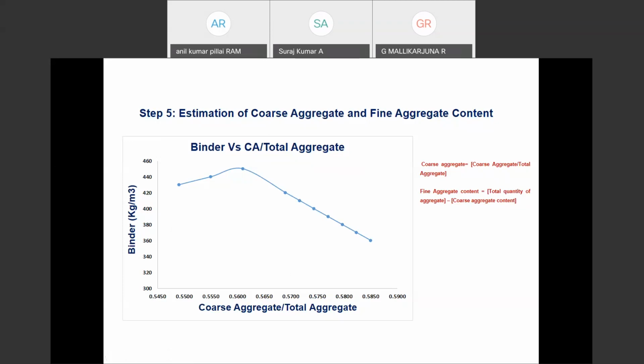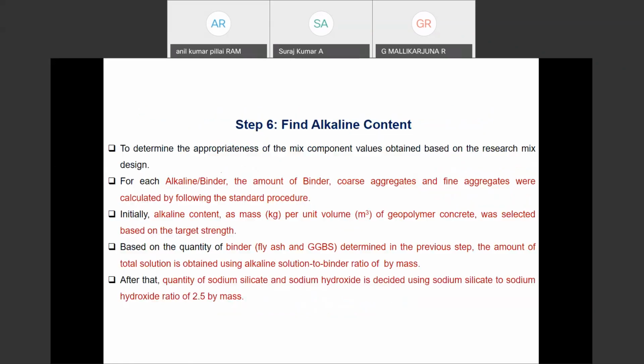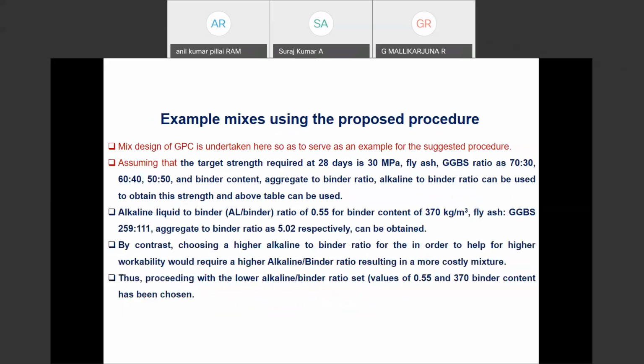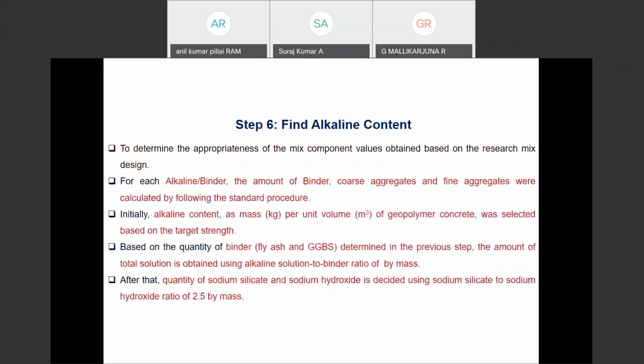fine aggregate content. We know the density, we know the aggregate to binder content, and we know the alkaline to binder ratio. Based on these things, once you deduct from the density the alkaline content, binder content, and aggregate to binder ratio, we are going to get the aggregate content there. Based on that, we are going to get the total quantities estimation. So that finally, I'll show you one calculation of how we had done this. And finally, we are going to get the alkaline content.